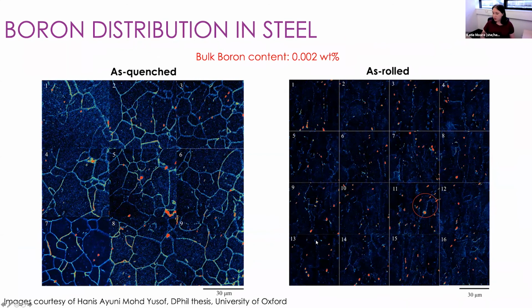And finally, I just wanted to show you something completely different, just to show that the NanoSIMS can do lots of different things. This is some work carried out by Hannes, who was a DPhil student of mine when I was back at Oxford. She was looking at boron distribution in steels with different heat treatments. So on the left-hand side here, we have an as-quenched steel alloy, and on the right-hand side, an as-rolled alloy. And what you can see here in terms of boron distribution is that there's very different boron distribution depending on the heat treatment.